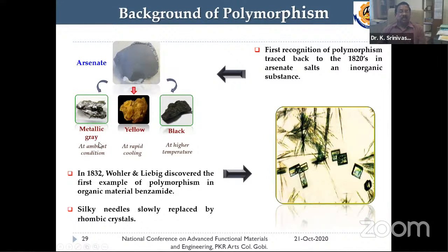When you cool it rapidly to lower temperatures, it becomes yellow, and it becomes black at very high temperatures. So with the temperature, it changes from one color to another color. This is just because of changes from one crystal system to another system. This was first recognized with arsenic in the 1820s itself.